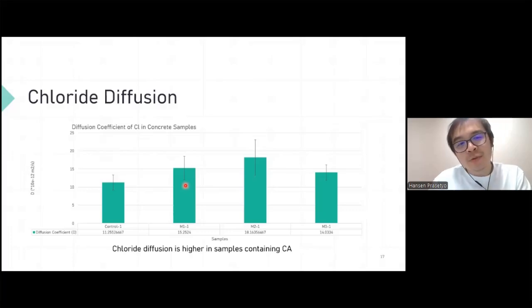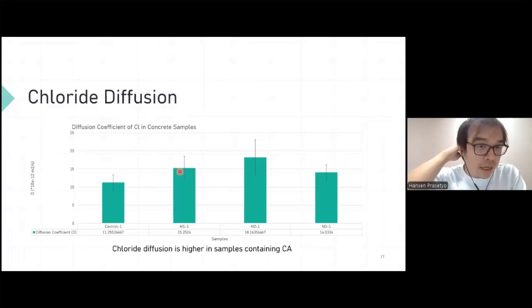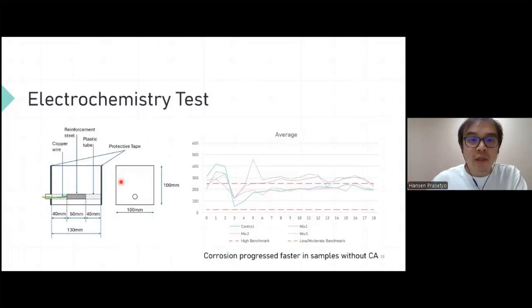So the result is, weirdly, we have an increase of apparent diffusion with an increase of CA. So that's not good. That means that when we add CA into the mix, we have an increase in chloride concentration, while it's supposed to be doing the opposite. But keep in mind that these samples are uncracked, and the increase is not very significant, right?